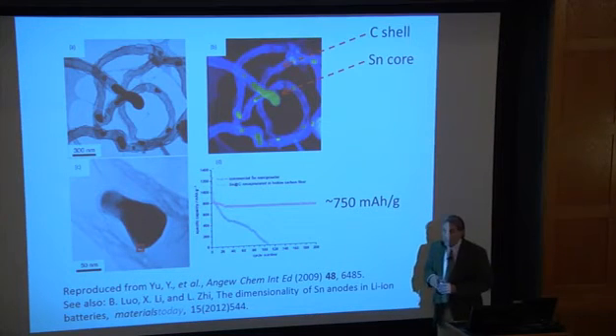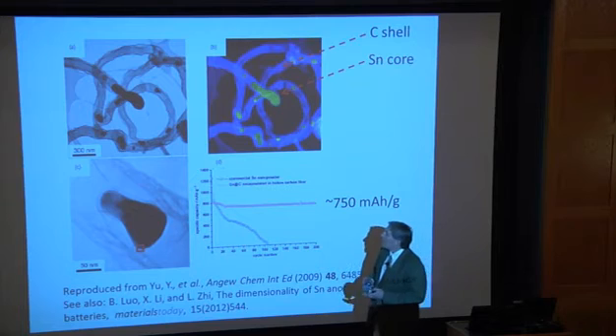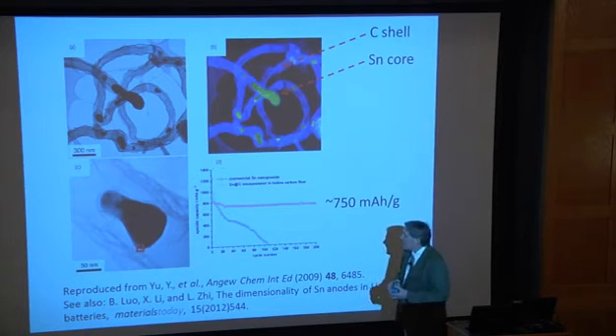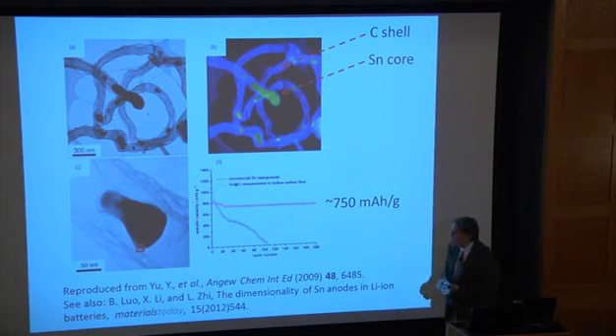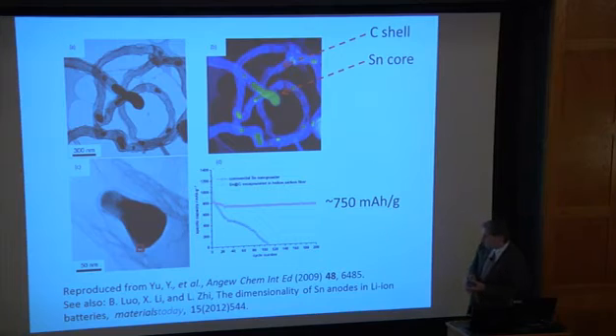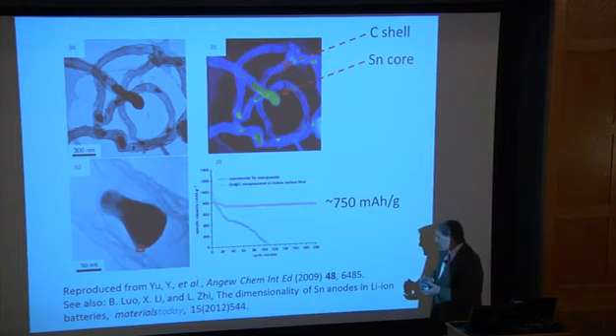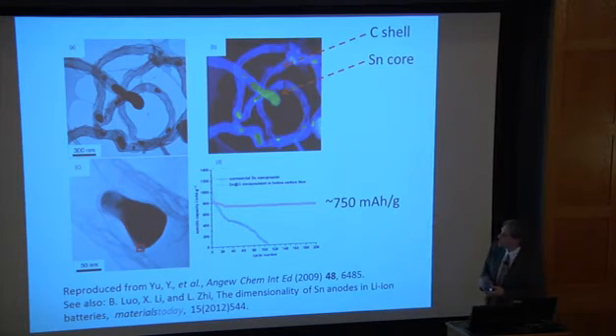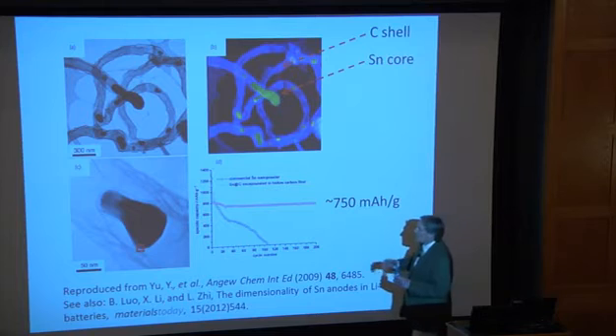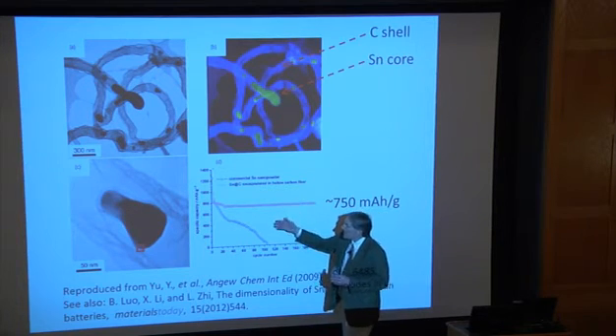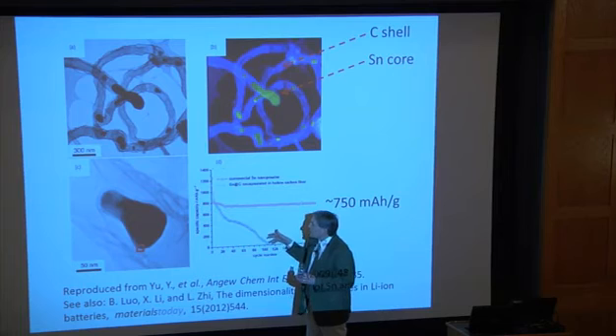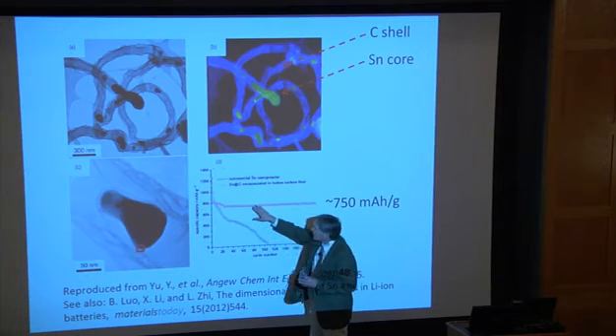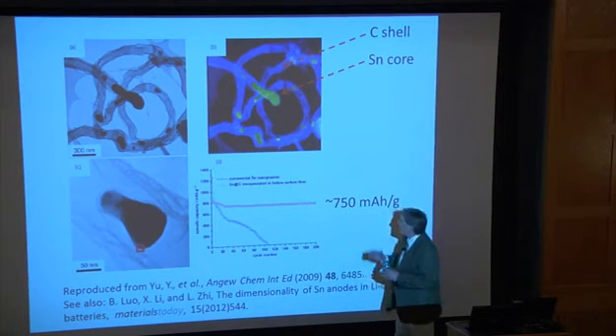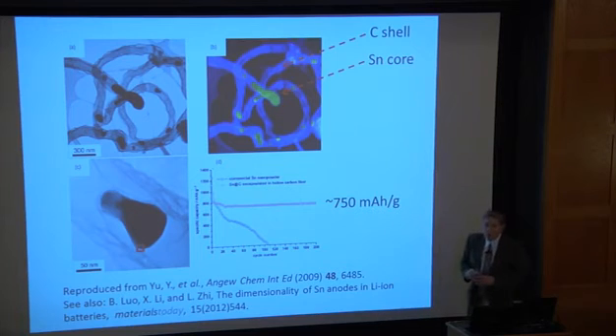So what are people doing to try to make these systems work? There's a lot of work on core shell structures, and this is just one piece of work. The title of the paper, if I remember correctly, I don't mention it down here, but it was concerned specifically with different core shell structures. In this case, they showed in particular a tin system. You could see without their core shell structure, it decayed rather quickly, and with the core shell structure, it hung up around just under 750 milliamp hours per gram, which is quite good for tin.